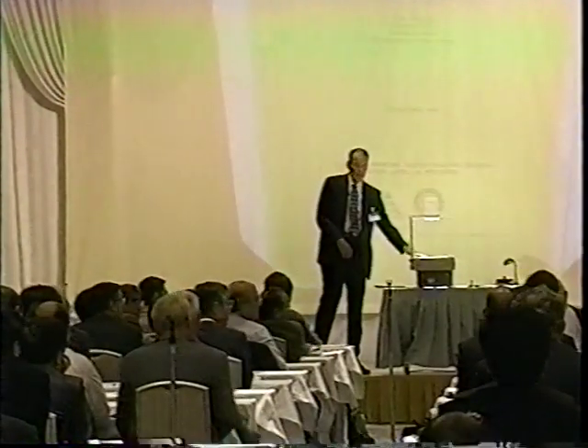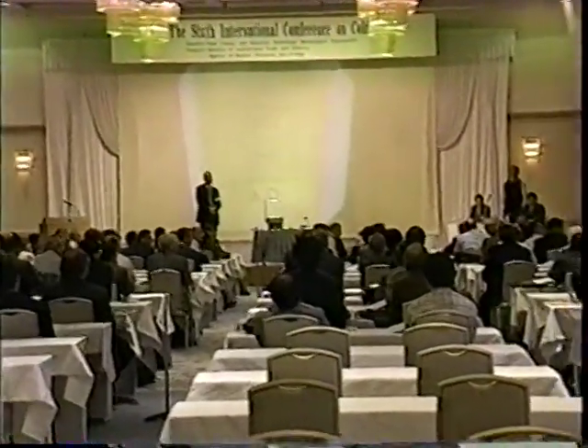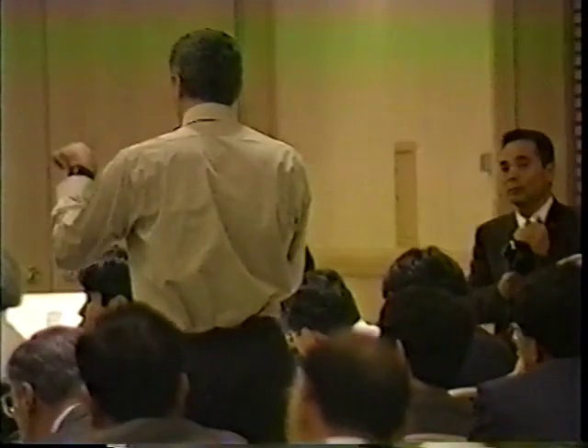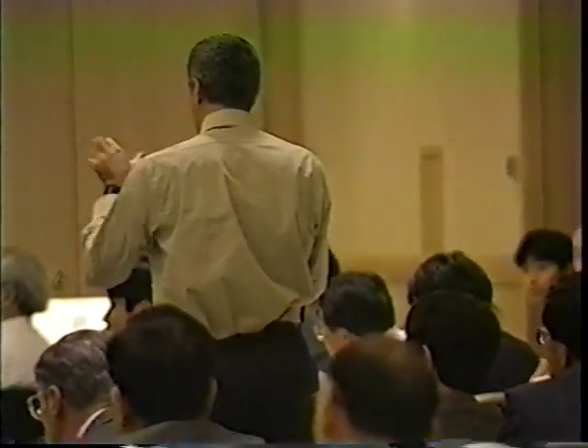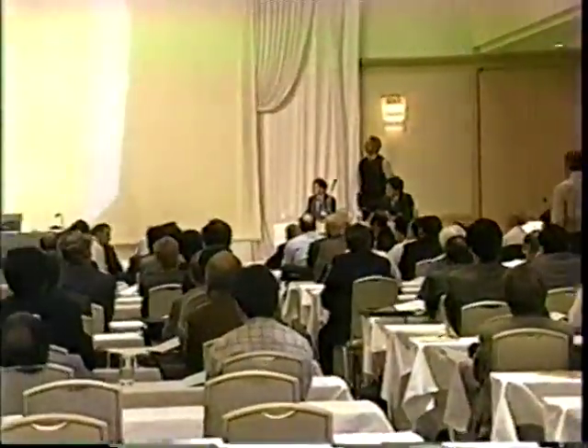Dr. Kucherov. When you show the slide of excess energy dependence on time, at the very beginning you have a negative excess heat. Does it mean that at the initial stage you store energy, or it's within the experimental error? It is experimental error. One of the posters we have later today shows an improved calorimeter that can measure plus or minus 1 milliwatt. And you can actually see in the initial stages the heat of absorption of the deuterium going into the palladium. When you look at the beginning stage of that, it tracks very close to zero. There is no negative effect really there. That is just experimental error that we saw there.